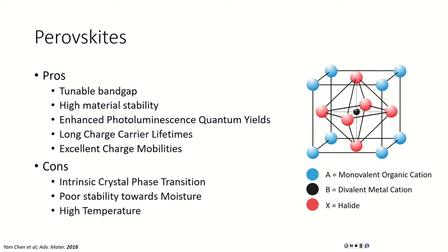These are also made at high temperatures, just not at the cost that silicon is. These are usually made around 400 Kelvin, 500 Kelvin, so nearly a third of what the conventional LEDs are, and they degrade rapidly when exposed to moisture. That's kind of hard whenever the whole world is water-based, and a high percentage of it is water.